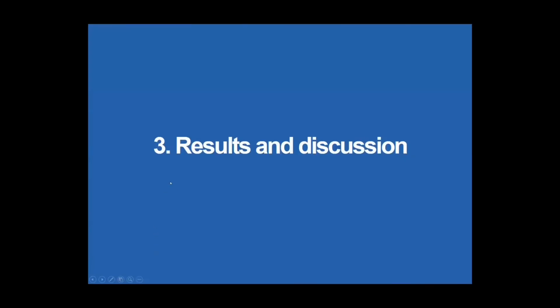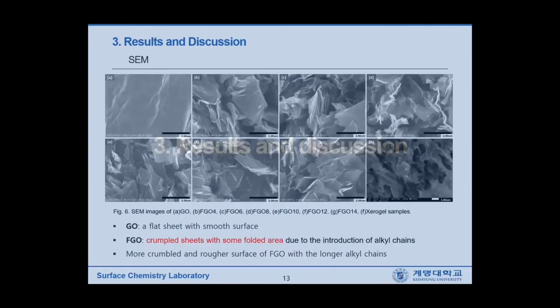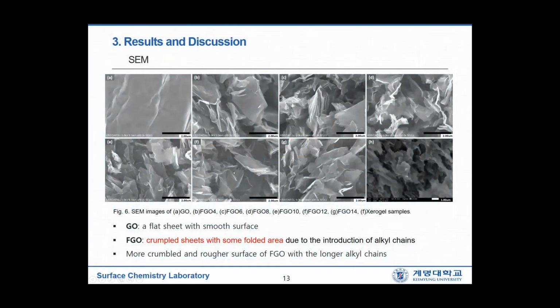Let me talk about results and discussions. This is a series of images taken from graphene oxide and functionalized graphene samples. GO shows a flat sheet with a smooth surface. FGO shows crumpled sheets with some folded areas due to the introduction of alkyl chains. It shows a more crumpled and rougher surface of FGO with the longer alkyl chains.